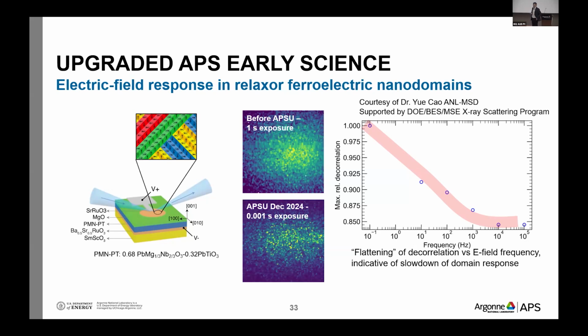So you can start to see the gains that were promised from this upgrade, certainly in XPCS, but also starting to see improvement, major improvement, I would say, in imaging as well, and coherent diffraction imaging in particular. So this is the single point that they could collect when running at just slightly below 1 hertz before the upgrade, and now they can actually map out this entire frequency response in a way that was simply not accessible before. So that's a huge improvement, and I'm sure when POLAR and other beamlines come along, you will see the same type of improvement, whether it's spatial resolution, speed, throughput.